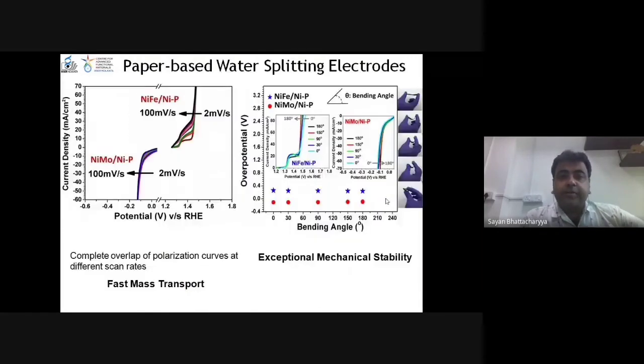And if you change the scan rate, this is one thing about electrochemistry, that you can do a lot of things. You can change the scan rate, the rate at which you change the voltage. Okay, so it is 2 millivolt per second. From here, you can go up to 100 millivolt per second. You see these curves do not change, and they more or less overlap here.